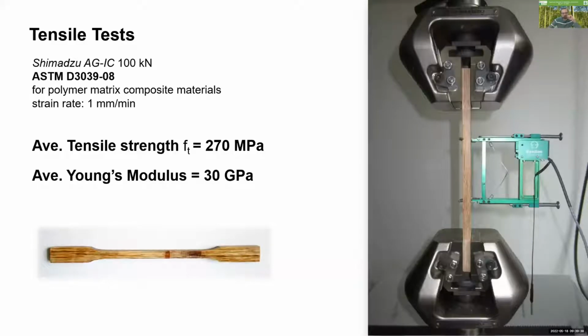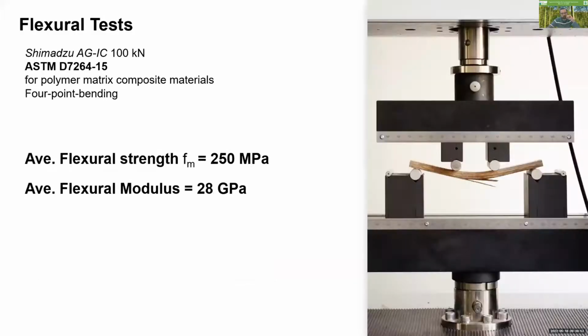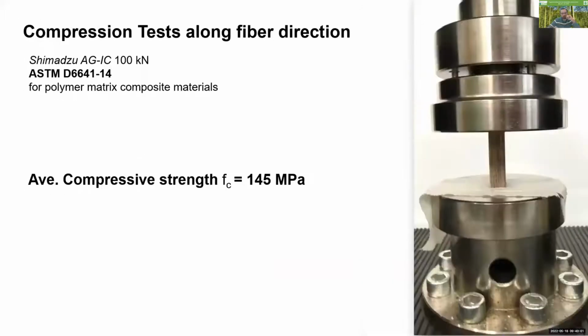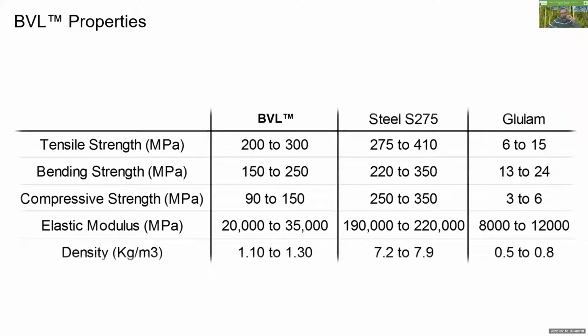So we did a lot of mechanical testing like tensile tests, and for this specific species, Dendrocalamus asper in Southeast Asia, we achieved a tensile strength in the range of 270 and a Young's modulus of 30 gigapascal. Similarly, we have done a lot of flexural tests or bending tests, and the bending test and the tensile test were quite close. And finally, compression tests we did along the fiber direction. Of course, the mechanical properties were quite interesting. So this is also a range.